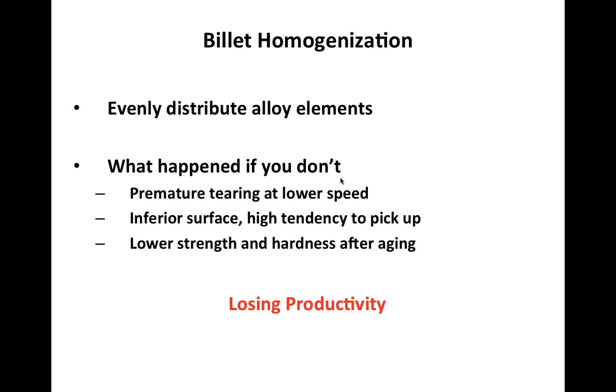So you need to evenly distribute the elements, and then you need to give it time and temperature, which we call homogenization. What happens when you don't do it is you don't have a uniform property of the alloy, and you have an inferior surface. Usually the surface has high iron content, and because of the different property on the surface of the billet and the core of the billet, there's a strength difference during extrusion, and there would be premature tearing at low speed. You just cannot get high strength and high hardness through a non-uniform alloy.